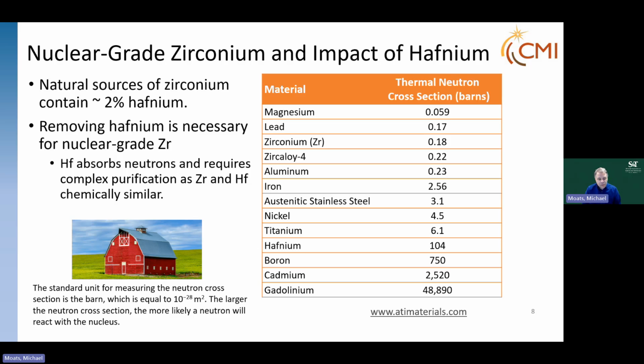In the early part of nuclear energy development, they were looking at materials like magnesium, zirconium, and aluminum because they were pretty low. But zirconium had a lot of variation, and as you'll see, that has to do with the hafnium. All natural resources of zirconium contain about 2% hafnium, so that's in zircon. And that hafnium, which you can see has about 104 barns, created quite a bit of variation in the zirconium that was produced, which led to the need to separate zirconium and hafnium.